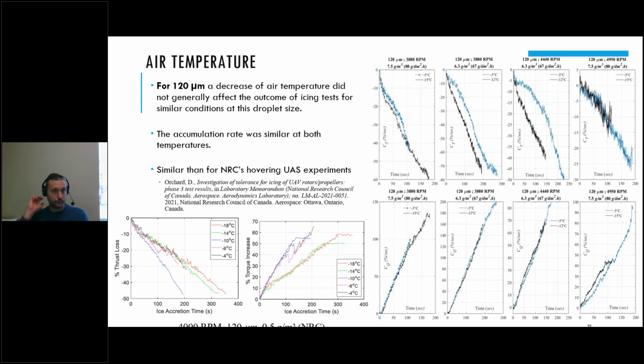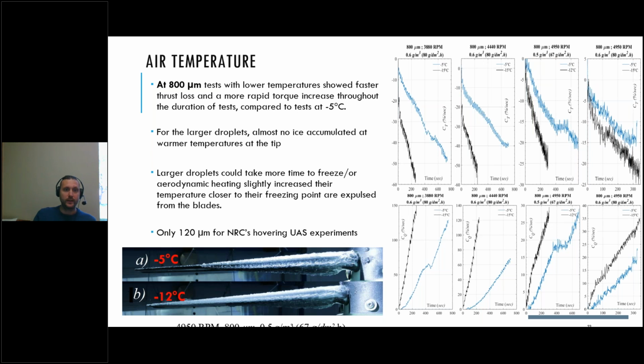So for the droplets of 120 microns, the decrease of air temperature did not generally affect the outcome of the icing test. Even if the ice type was different, the performance degradation was similar between the different temperatures, and it was similar to observations also made by experiments at the NRC on UAS experiments, as you can see on those pictures. So it was consistent with their results as well. However, next slide, please.